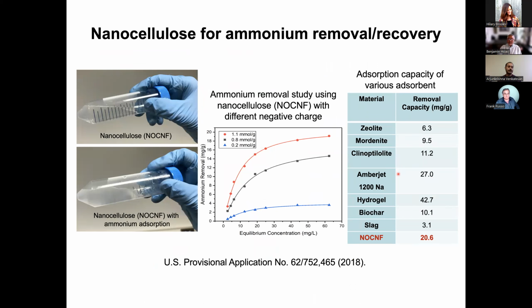And for the longest time, I always thought that in the wastewater, the ammonium part, typically from urine, if you can do a phase separation, is a way we can actually recover this ammonium as an upcycle of all the nutrients. So we actually tried to use our negatively charged nanocellulose to remove ammonia materials and to recover them. We have a patent application, but this is just to show that the removal capacity of our NOCNF is pretty high, not as high as synthetic hydrogels, but it's high enough. But these materials can be reused as a fertilizer as well. It's really good for fishery or wastewater treatment.